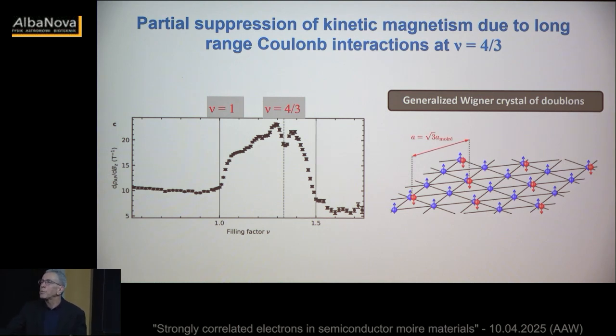So you see the main problem with moire structure, again, different levels. The single layer structures, the success rate is essentially 90%. So you have to have something going wrong with the contacts, that we usually use graphene, could slide away, and then we cannot contact, and that's a failed device. So once you go to moire, the main difficulty is whether you can actually reach the targeted twist angle, and then how much the twist angle varies over the sample. This is particularly challenging for graphene because they need the magic angle. Here there is more flexibility, but then the material disorder is worse. So I don't know if it explains the 50%, but yeah.